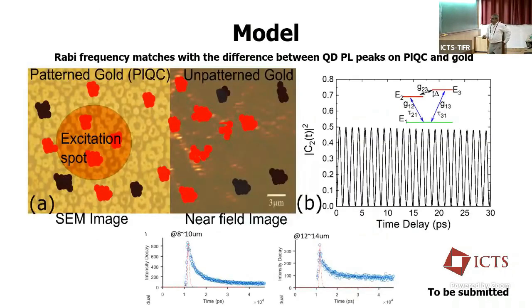We did the full Rabi Hamiltonian calculations, and the model we are proposing is that we are exciting quantum dots on the patterned metal surface, and these quantum dots are emitting, which excites the plasmon modes, and these plasmons propagate and excite quantum dots at a faraway distance. So we have long-range dipole-dipole interaction mediated by the plasmons in this case. From near-field studies, we show that indeed we do get emission from quantum dots almost 20 micrometers away from the edge of the excitation spot.